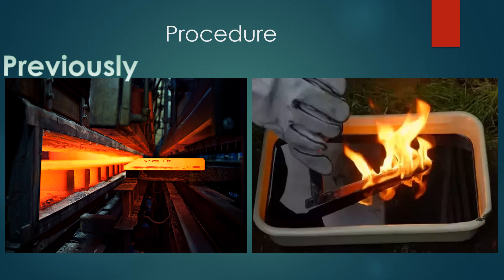Initially, the techniques of manufacturing bioactive glass consisted of heat treatments then quenching to freeze the atomic structure. But this technique proved to be flawed and ineffective since high sintering temperatures reduce the bioactivity and ion dissolution. Heat treatments also cause the formation of crystalline phases in the glass that severely decrease the elastic modulus and strength, leading to easy fracture and failure.